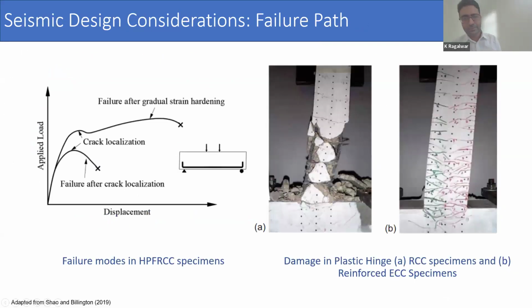So moving on to our last part, we'll talk about seismic considerations. So as we have seen till now, unlike the conventional reinforced concrete, which typically fails through cracking, reinforcement yielding, and then crushing or fracture, reinforced HPFRCC exhibits two distinct failure paths identified by research done by Shao and Billington. The first path is basically failure after crack localization. In this case, the crack initially forms through multiple fine cracks due to pseudo strain hardening behavior. When the fiber bridging weakens at the most critical crack, localization occurs, which we have talked about. If reinforcement hardening cannot fully offset this loss, the beam's capacity also drops after localization, ultimately leading to reinforcement fracture, which is happening here.